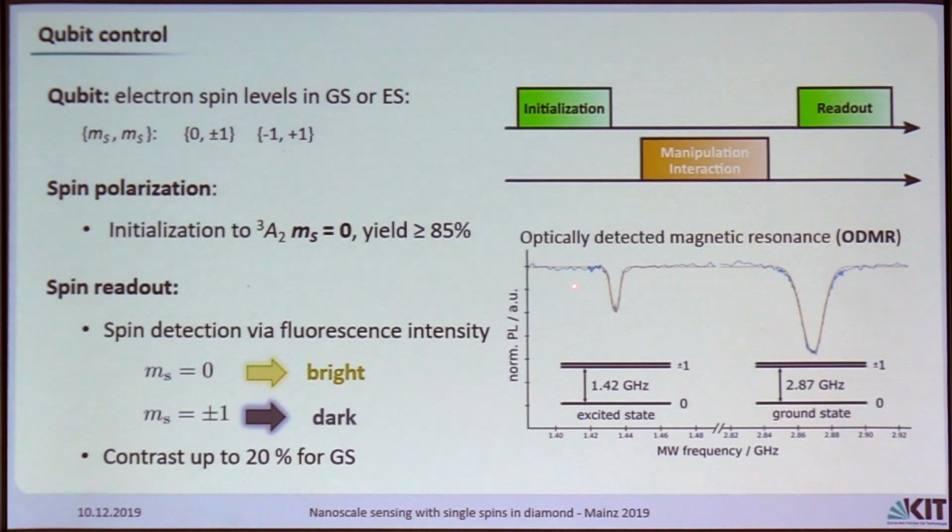And we can really see this in this ESR type experiment. So it's just that we apply a microwave externally and sweep the frequency. And once we hit the resonance frequency of our state, we transfer population from zero, so the initialization, up to ±1 in the excited state.